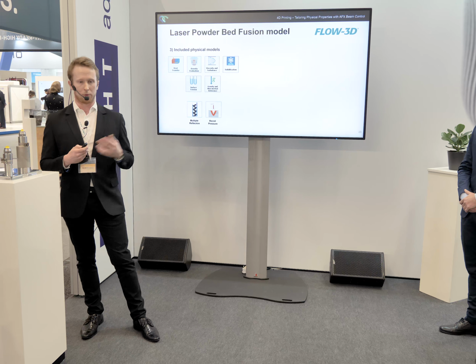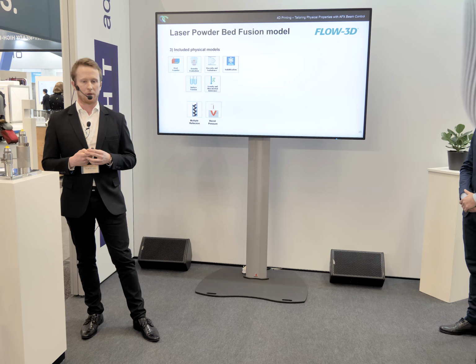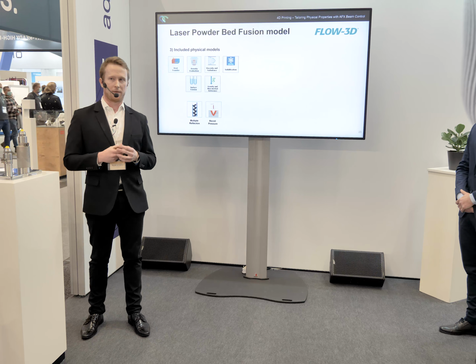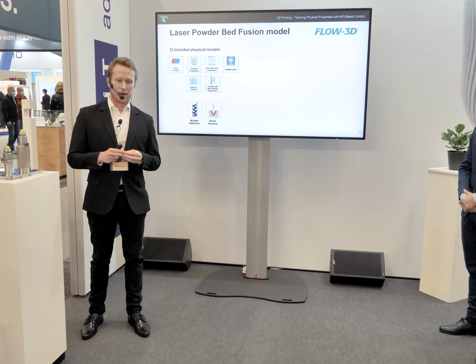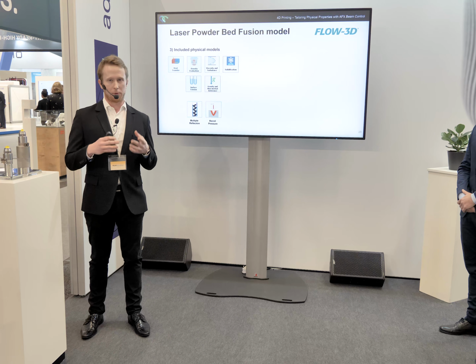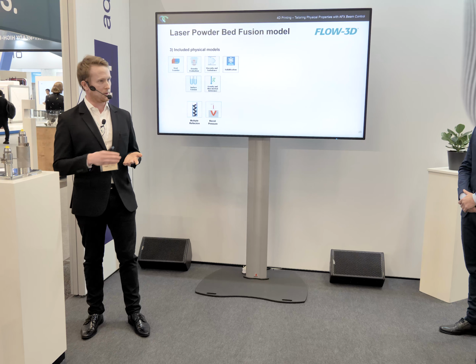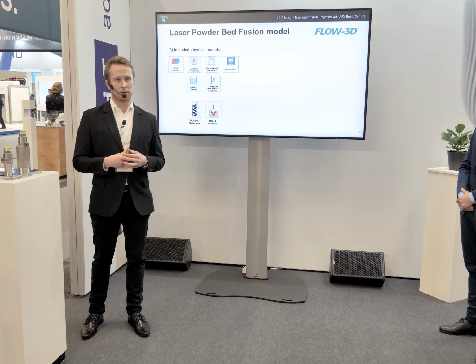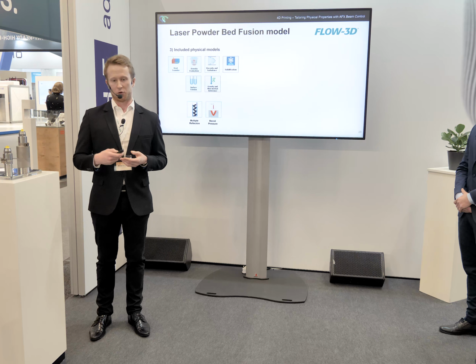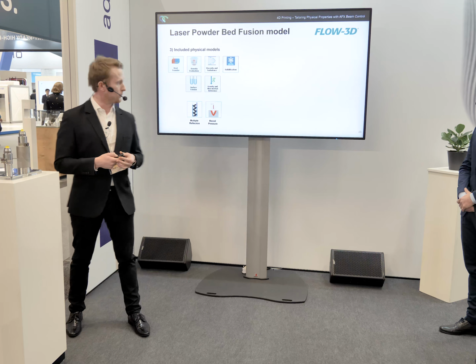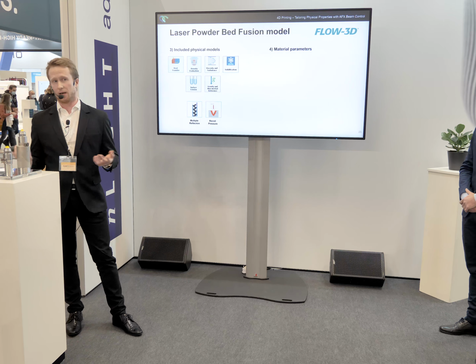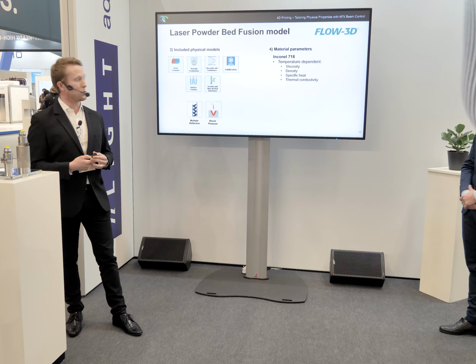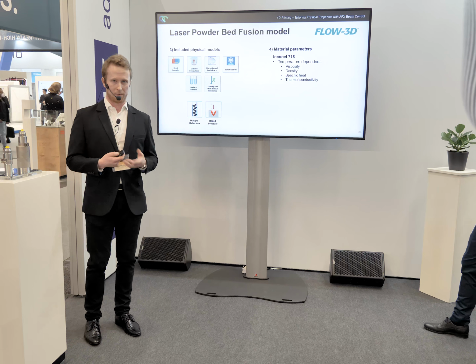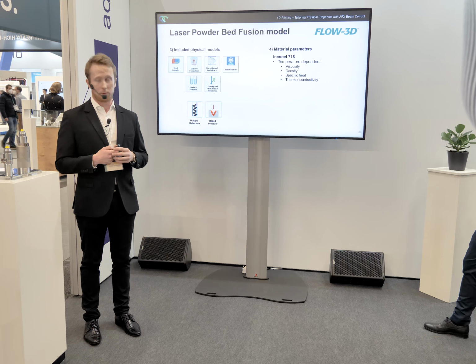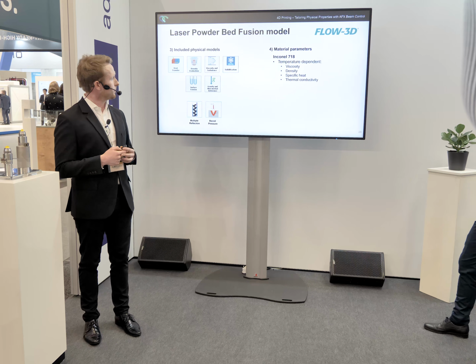We also included in this model the recoil pressure model, which accounts for the fact that the evaporating liquid metal expands very rapidly, and it creates a force on the free surface of the molten material. And that actually is one of the important drivers of the flow inside of the melt pool. As in any simulation, we do include, of course, the material parameters of the material itself. In this case, it was Inconel 718.